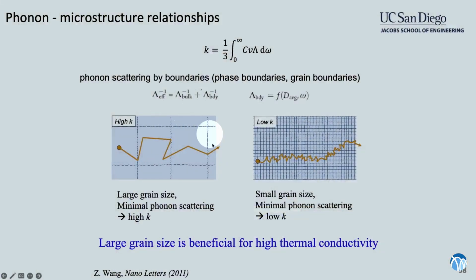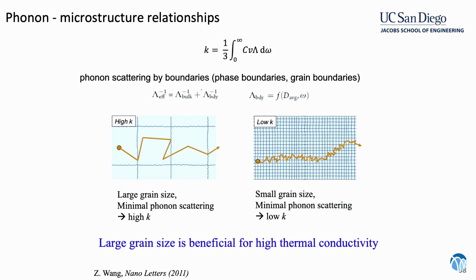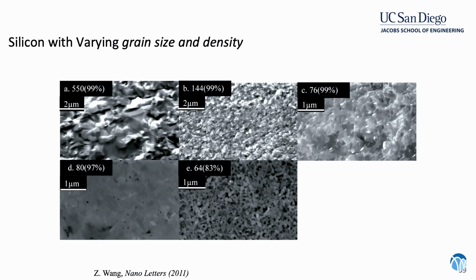So let's put in the microstructure. If I have a material with large crystals, like large crystal size like this, then the scattering, that mean free path, how far I can go before I change directions, is long. Now, as I put in more grain boundaries, I start increasing the number of scattering sites because the phonons are now scattering off of those interfaces. The mean free path is shorter, so your thermal conductivity is lower. So again, when you expose materials to neutrons or to high energy sources, you change this microstructure, and you can change something like thermal conductivity, which is very important to the properties that you're looking for.